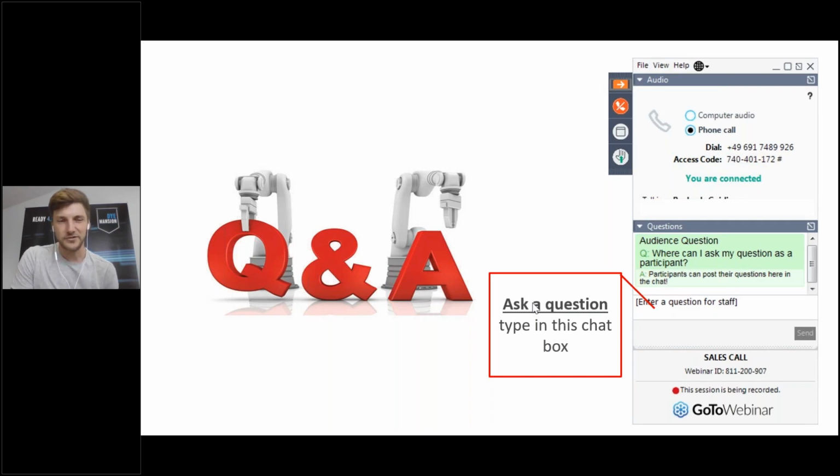Yeah, that's a very good question, and I think that's where the DyeMansion technologies really shine, both the PolyShot surfacing as well as the VaporFuse surfacing. Maybe we start with the PolyShot surfacing. Most of us are familiar with the tumbling process of parts, and that's an abrasive process, so you remove material especially from the edges and the corners. That's why we came up with PolyShot surfacing, because it doesn't remove any material from the parts. It just compacts the surface. It shoots plastic media with high pressure onto the part, and that levels out all the ups and downs in the surface and makes it homogeneous from upskin to downskin. This way we can conserve all the details on the part, because we are not removing powder.